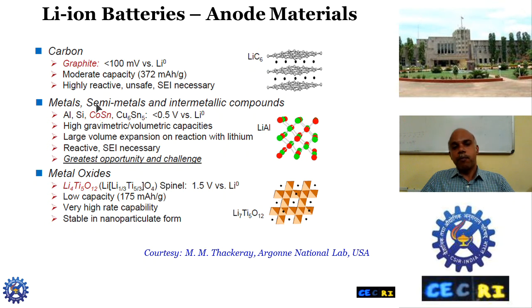The problem comes, for example, if you take silicon or tin, the volume expansion leads to the short circuit of the cell. By having a carbon coating, we can minimize that, so that carbon can act like a buffer layer. And similarly, the metal oxide, for example, the spinel lithium titanium oxide, shows a better performance and is stable even in the nanoparticle form. It shows 1.5 volts versus lithium as an anode material.